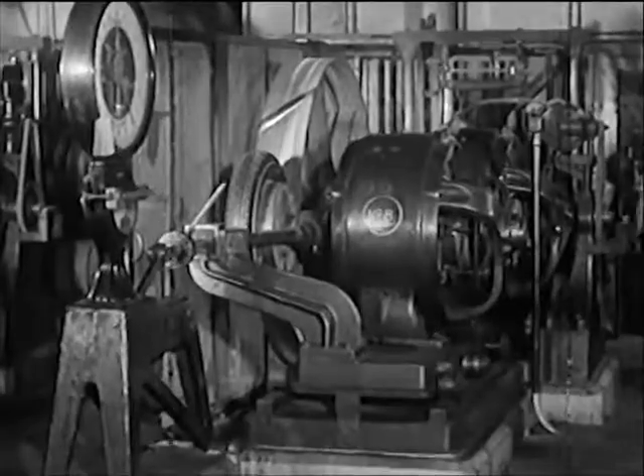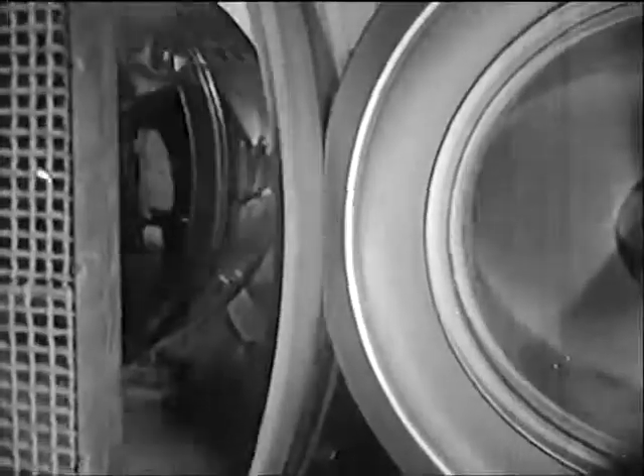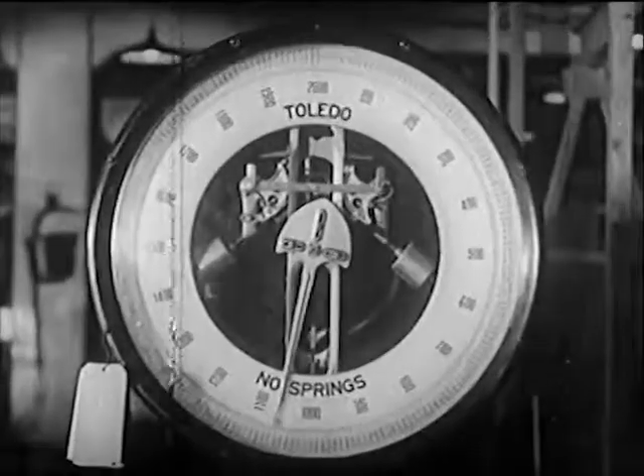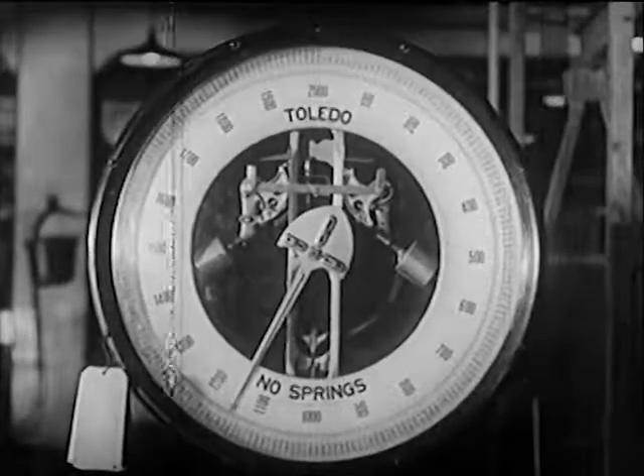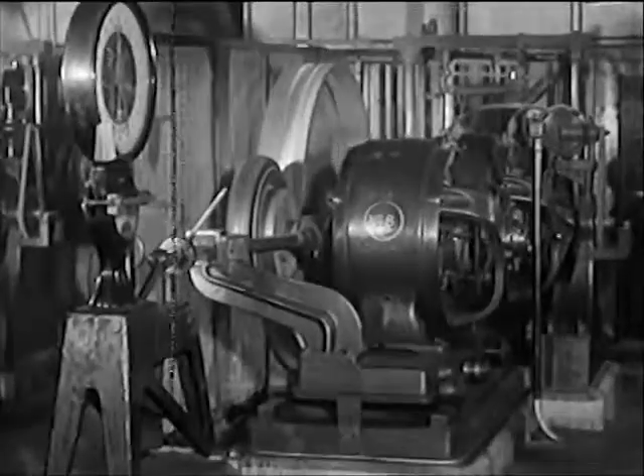For the equivalent of thousands of miles, these tires are driven on and on for days at a time. Imagine the heat generated in the tires with the incessant pounding of the cleats, and every part of the tire pounding and flexing about 2,000 times a minute. The heat of the run expands the air inside the tire, forcing even greater pressure against the dynamometer wheel. Under these conditions, an ordinary tire soon fails. But the Brunswick Super Service, when put to this test, proves definitely its resistance to destructive high-speed flexing by running continuously for the equivalent of 10,000 miles without failure.